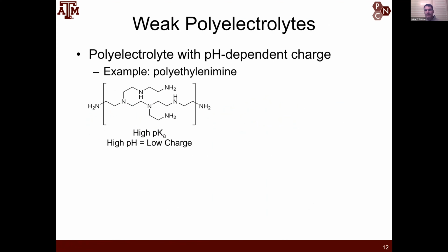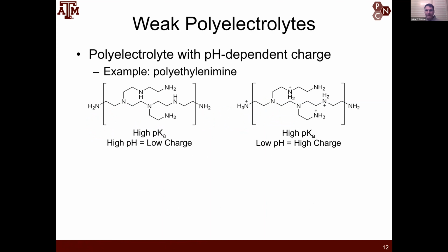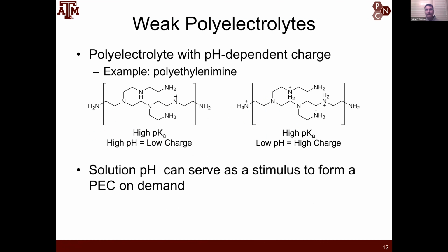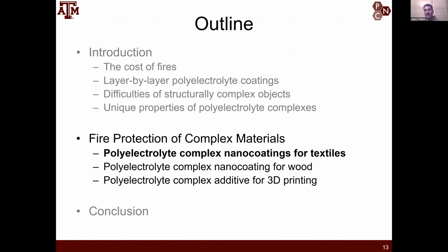But I also need to be able to process a stable solution from water and then apply this complex to a surface. So what we do is we use weak polyelectrolytes so that we can adjust the pH just before we form the complex. And the pH adjustment will create the complex. Therefore, we can coat a material and then adjust the pH, and then we will have the complexed coating that is flame retardant. So I'll highlight this in 3 applications.